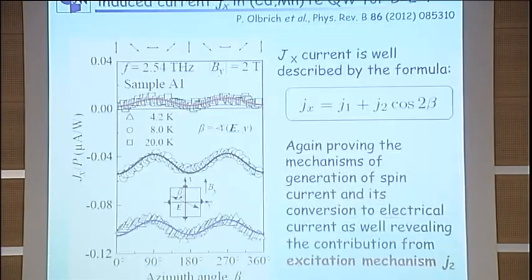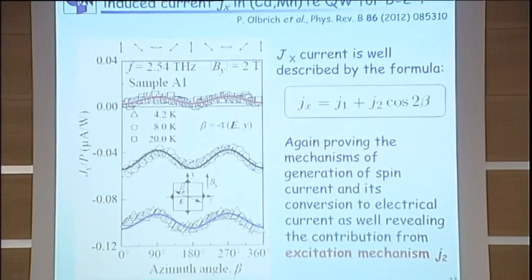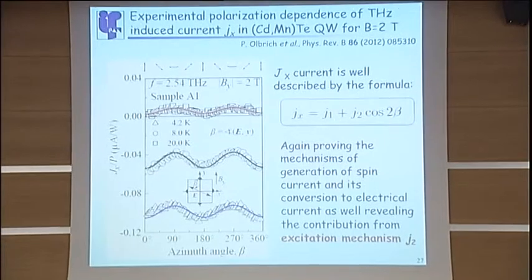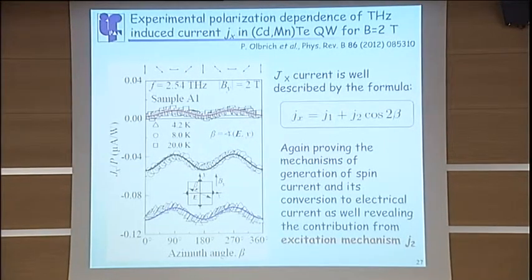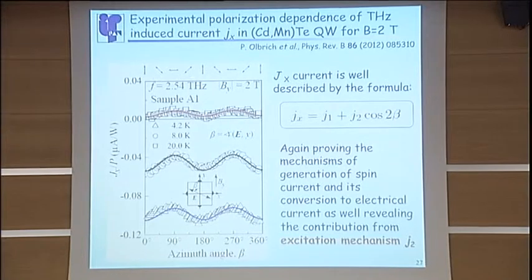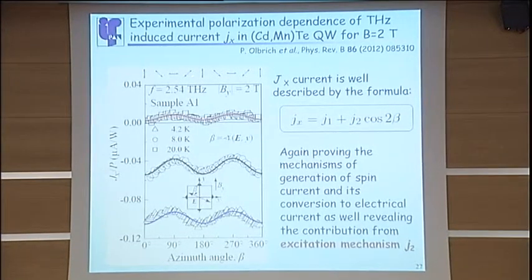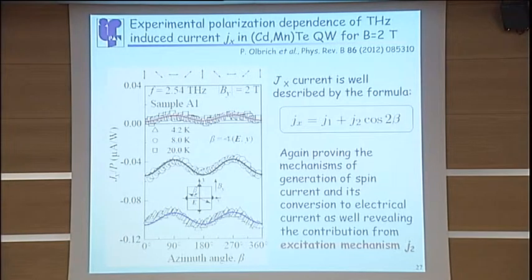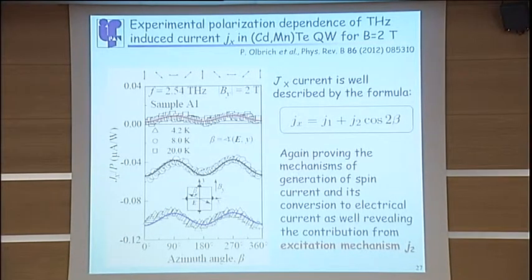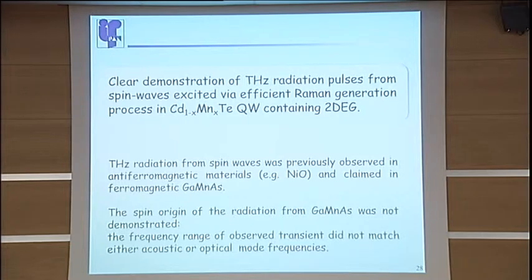Now, in order to demonstrate, on the other hand, this contribution of the excitation mechanism, our colleagues from Regensburg performed studies as a function of the angle between the polarization axis and the direction of the crystals, and they have shown that, in fact, this formula nicely describes the experimental data. Now, the next application of our structure with 2DEG: a clear demonstration of terahertz radiation pulses from spin waves, which are excited in our material by an efficient Raman generation process.